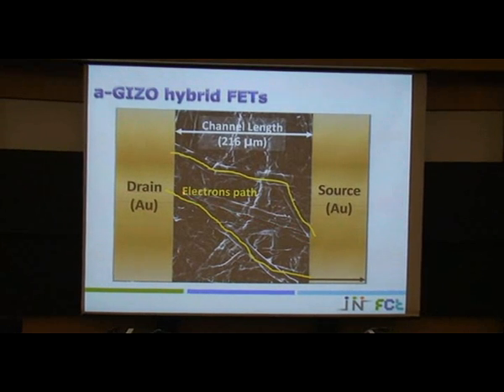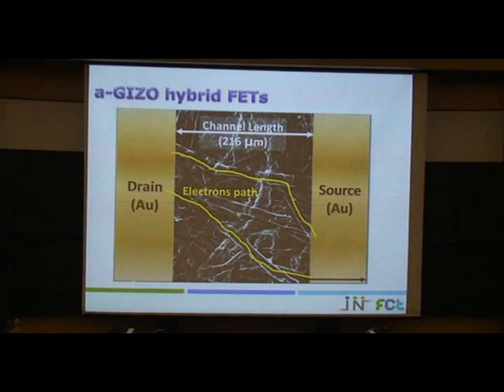And since we have this type of fibers, we believe that we have some preferential paths, ways, for the carriers, the electrons. And that's why we achieved on this type of structure such a high value of mobility. That's one of the explanations that we have at this moment, because otherwise it's hard to explain why the mobility is so high in this type of structures. Because the scale here is micrometers, but the material is covering all these fibers. So the fibers are covered with the material that we are depositing by sputtering.